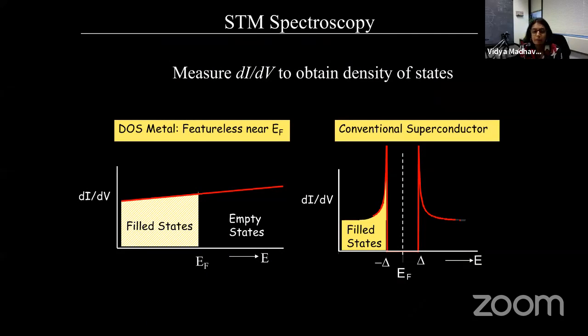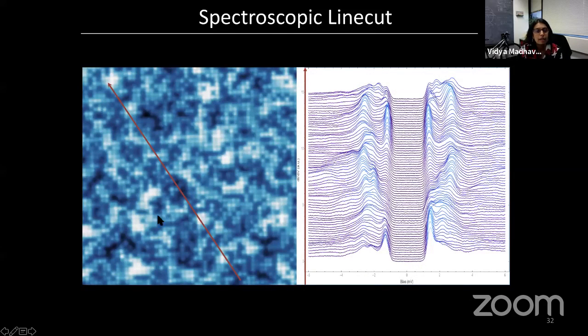Okay, so what do you expect to see? We measure density of states by measuring the differential conductance, dI/dV. For an S-wave superconductor, what you expect is coherence peaks and then the density of states going to 0. The position of the coherence peak tells you the value of the gap. So that's what you expect to see.